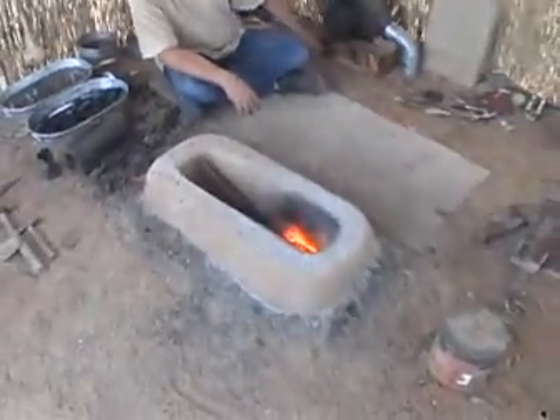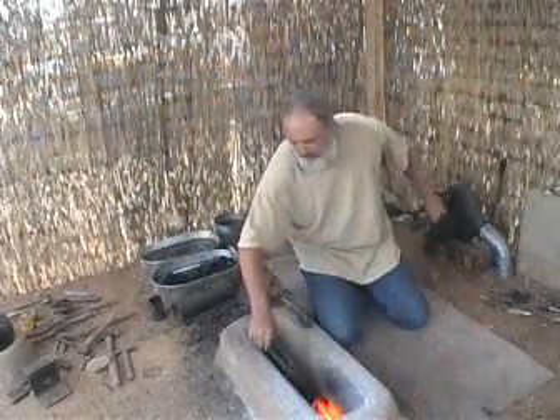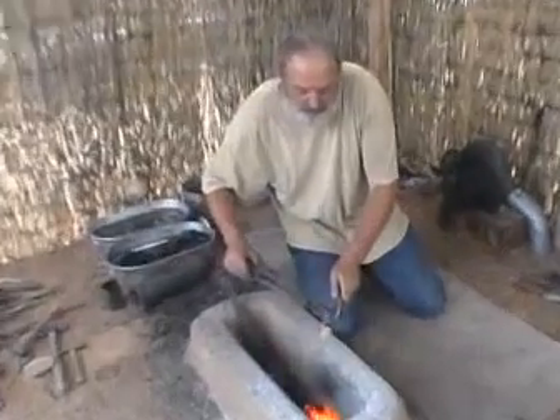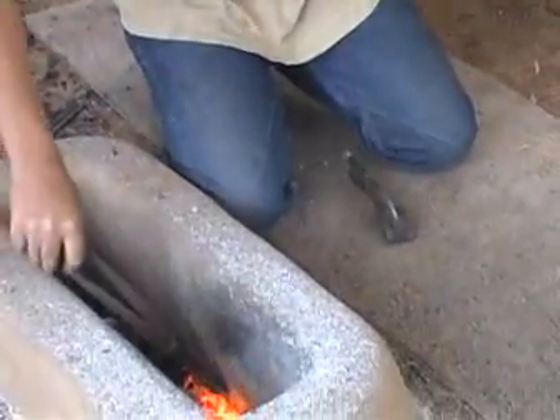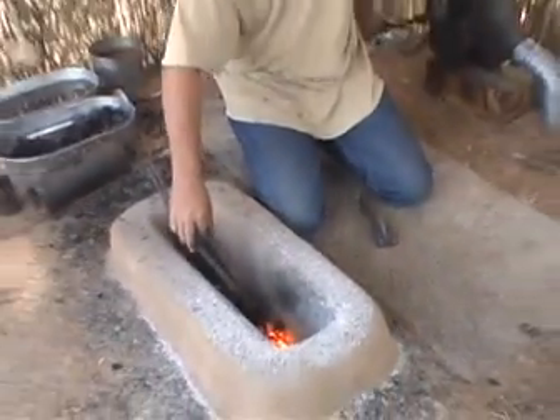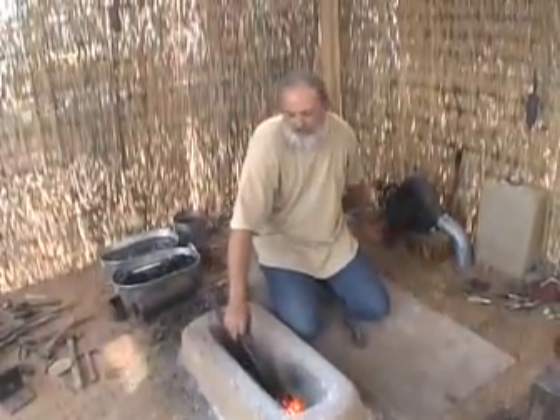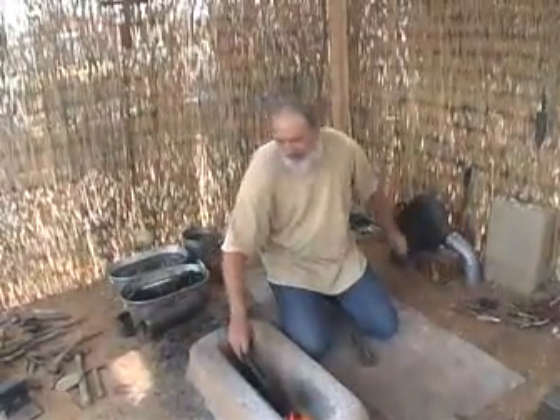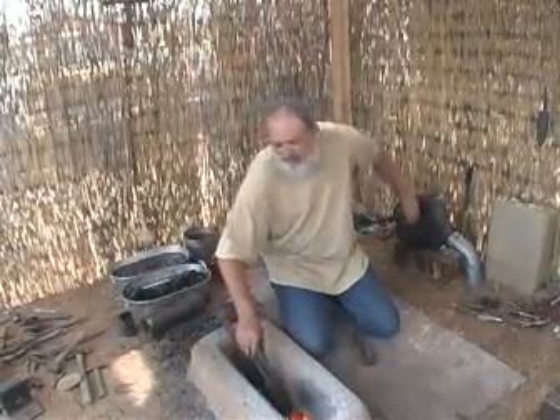So right now I'm just bringing it up to a nice even non-magnetic heat. Bring it up to a nice even heat and keep checking it with your magnet. When it's non-magnetic, then you're at the critical temperature. As long as it's nice and even, you're ready to quench.